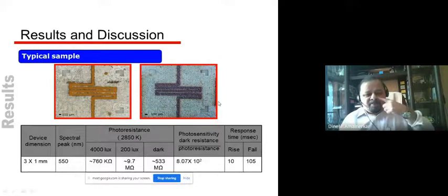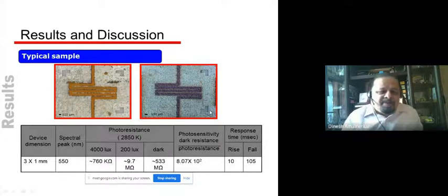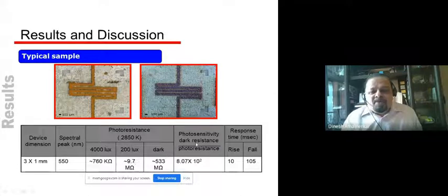Now let us quickly summarize our results for a typical sample. These are the device dimensions. Spectral response we have seen at 550 nanometers with a shoulder at 650 nanometers. These are the photoresistance values. What is photosensitivity? As I said earlier, dark resistance upon photoresistance, we get a value of 10 raised to 2 for this microphotosensor. But believe me, in my own case, where I work on bulk photoconductivity, I have got the highest reported value in the world, almost 10 raised to 9. But this is a microphotosensor with certain limitations. Most importantly, its rise time is just 10 milliseconds. Although the fall time is 105 milliseconds, the rise time is very important.